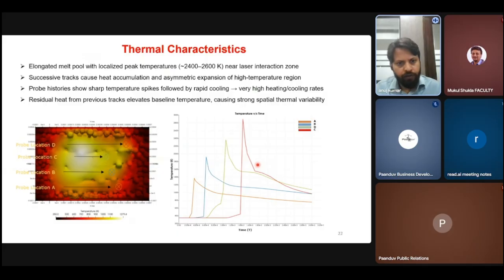These are the results which I am going to show for the study. We have taken certain process parameters from the existing studies. We try to simulate, we try to imitate that process in our modeling environment. We take the same material properties, we take the process parameters starting from laser power, scan speed, layer thickness, hatch spacing, and so on. We have spot diameter, we have density of the powder particle, we have convection coefficients as well. And then we try to obtain the thermal history, how the thermal history is going to happen.